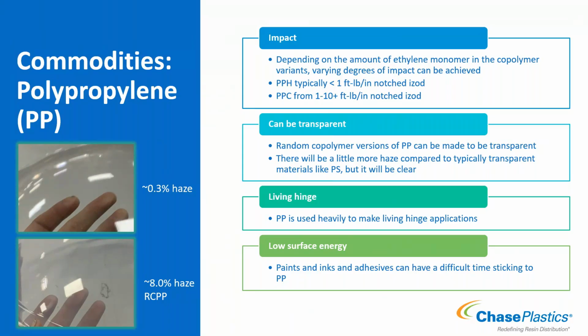Depending on how much we use and how we do it, we can affect the impact of the material. So polypropylene as a homopolymer can start with an impact as low as under 1 foot-pound per inch notched Izod, and get all the way up to no break, or plus 10. So we can really vary its performance and impact depending on how much ethylene is in the material and how that's processed.